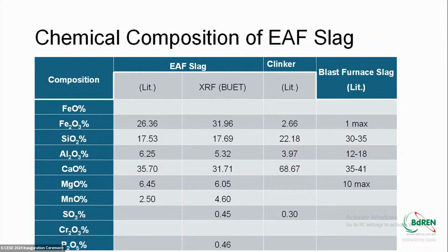If we see all other compounds, this is the average amount of different compounds found in EF slag according to literature. In our particular sample, the percentages were like this. If we compare with clinker, the major difference in EF slag is that a huge amount of iron oxide, ferrite, is present compared to blast furnace slag. Ferrite is almost nil in blast furnace slag.